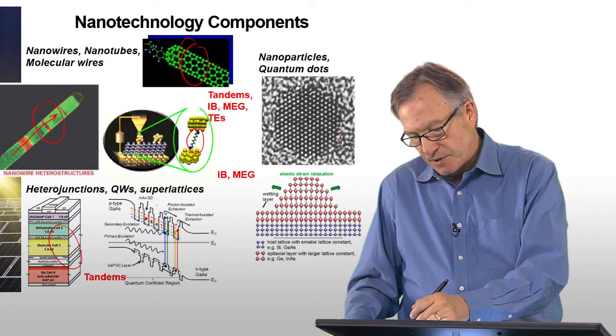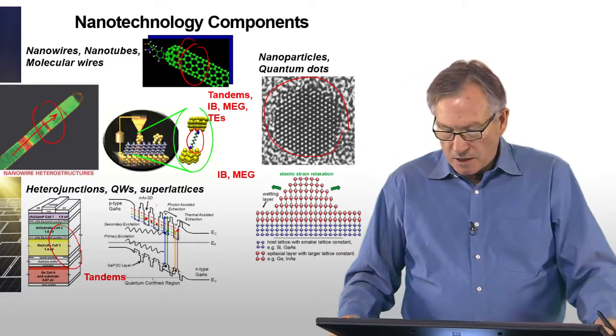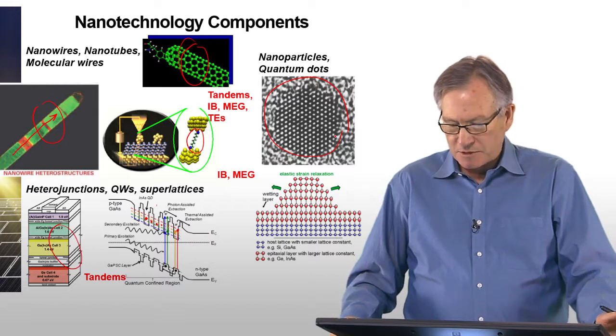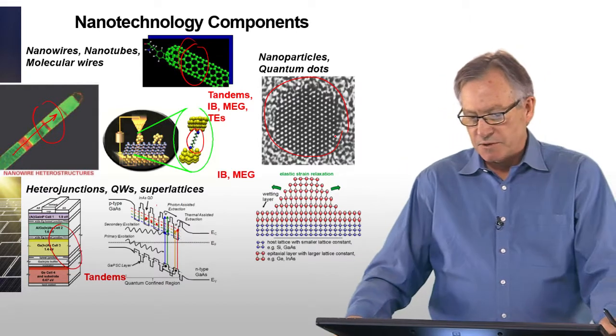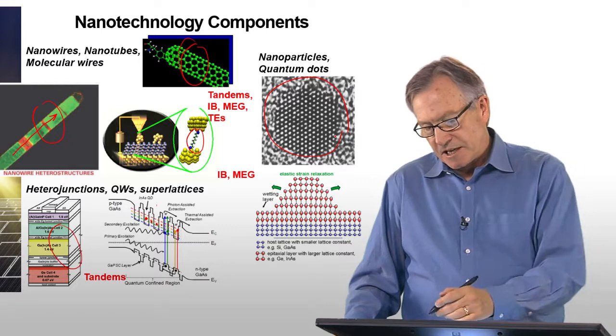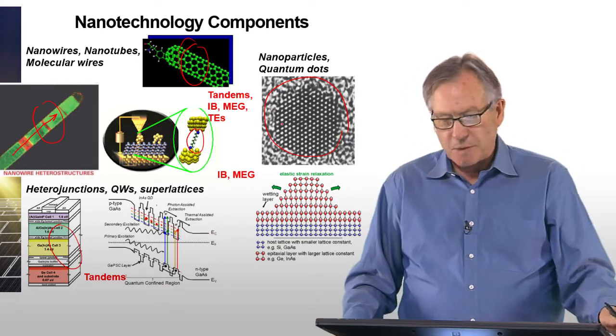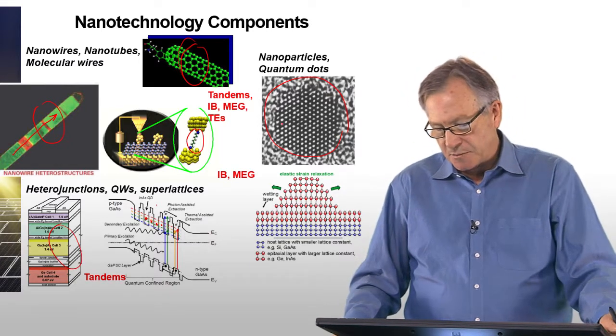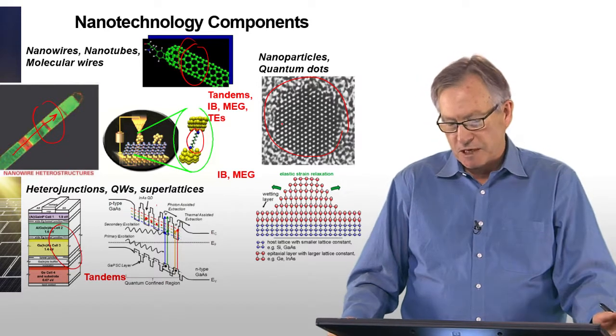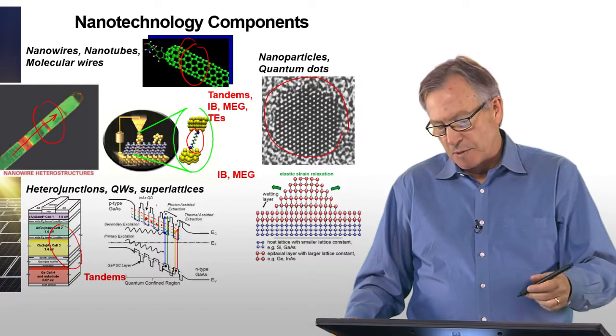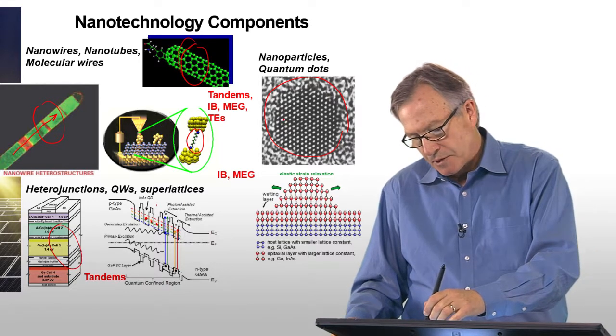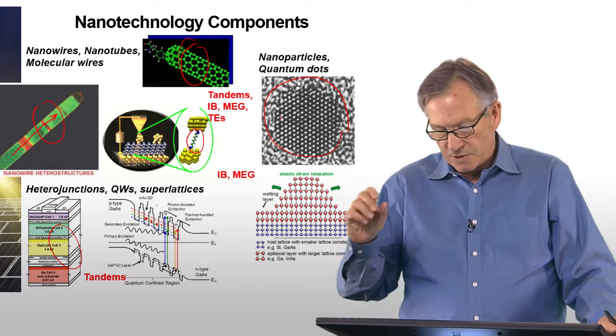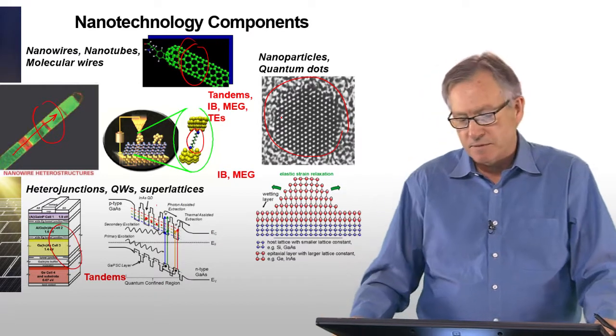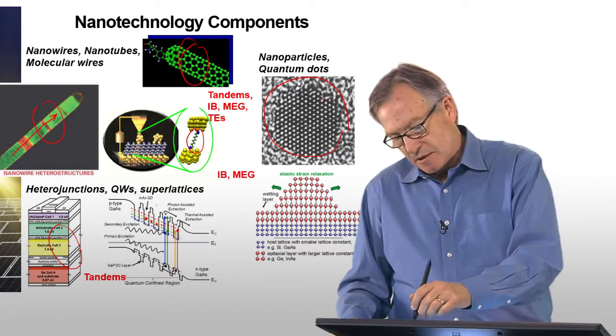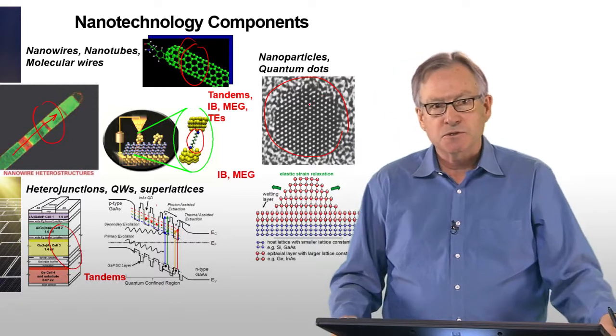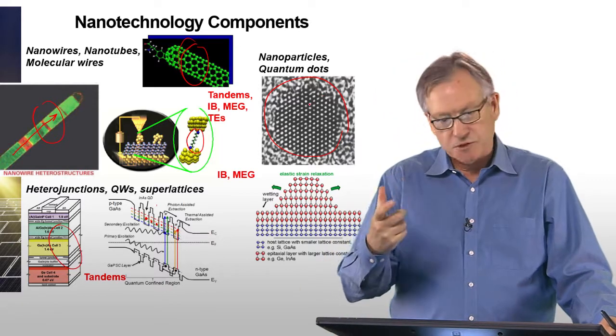What's shown here is a nanocrystal of, I'm not sure what material, probably this could be a silicon nanoparticle embedded in silicon dioxide. But in any case, this is an electron micrograph image, a lattice image using high resolution electron microscopy. And in high resolution electron microscopy, you're actually looking at either individual atoms or the molecular basis pair of the underlying crystal. And so you can see that there's a spherical object which has a regular crystal structure which forms a stable structure called a nanoparticle.